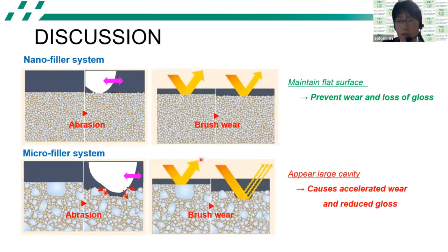In general, wear and gloss can be controlled by the particle size of the contained filler. This slide shows an illustration of wear and gloss of nanofiller and microfiller systems. In the case of a nanofiller system, the surface stays flat, preventing wear and loss of gloss. On the other hand, in the case of a microfiller system, large cavities appear due to filler detachment and cause accelerated wear and reduced gloss.